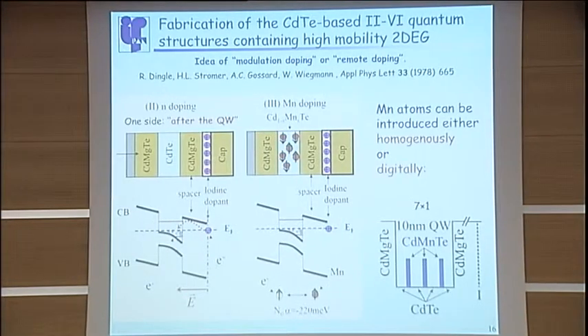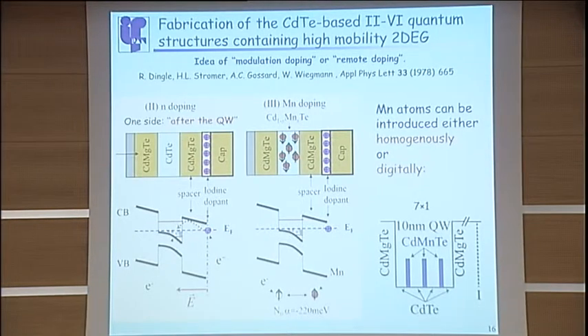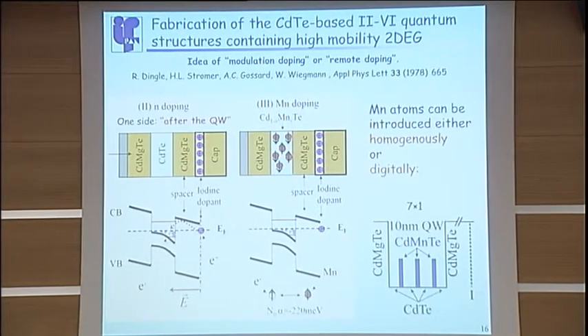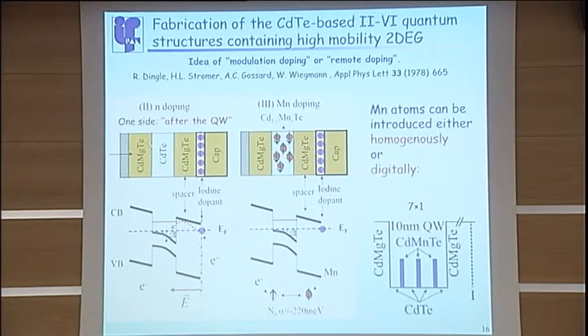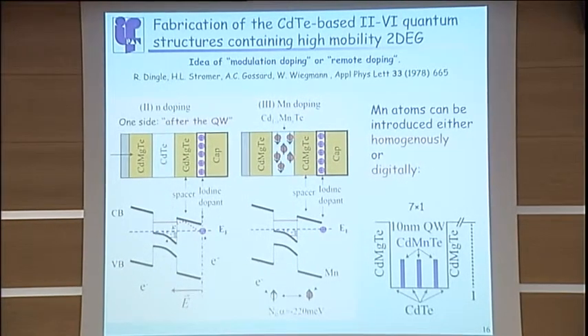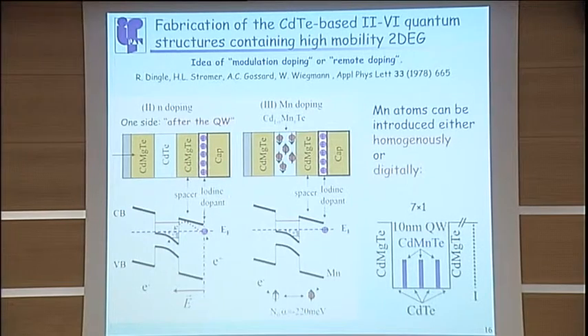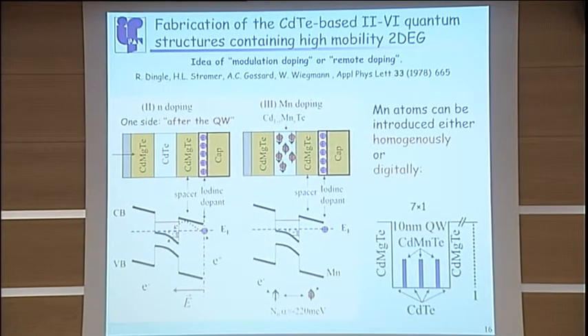Let me start by letting you know how we produce such two-dimensional structures. Of course, in gallium arsenide structures, you use gallium aluminum arsenide as a barrier. Here we use cadmium magnesium telluride as a barrier material. And we use iodine as a dopant because iodine likes to segregate toward the growing surface. Until very recently, until 2 days ago, we normally introduced iodine after the growth of the quantum well, so the donors will not go into the quantum well region.